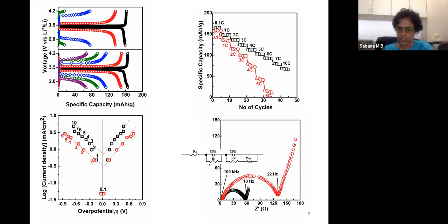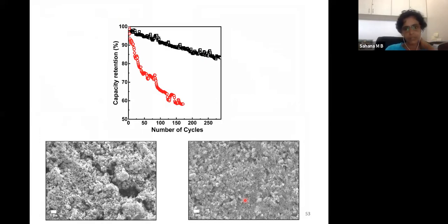When the mixing is not good, for a given material, it's a commercial material, commercial LiFePO4, the intrinsic properties are very good in both the samples. Just the mixing alone, just the electrode alone, where mixing is not good, the charge transfer resistance is very high, around 120 to 130 ohms. Whereas in this case, it is only half of it. And because of that, what happens?